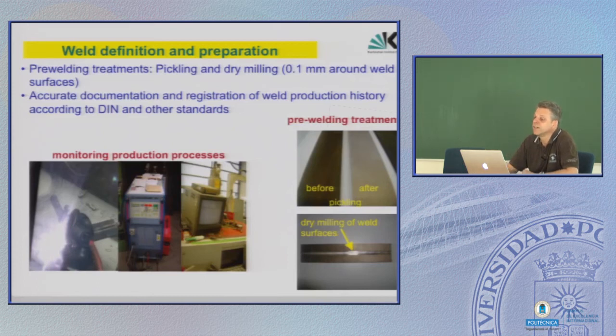That's why we avoided them and said, okay, perfect surface. For a perfect surface, you have to dry mill a little bit of the surface without any liquid, then it's shiny and perfect, and then you have to hurry up and start with welding. This was preparation in all cases.